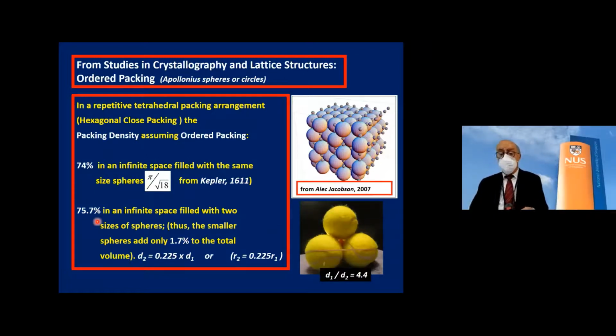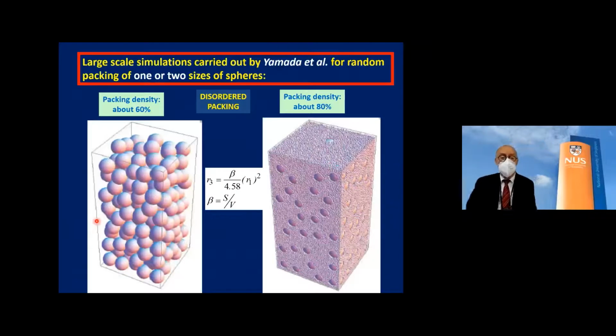But that tells you that if you want to increase the packing density, you better think hard about it. So now I go to this study, which was carried out by Yamada, I guess, can't remember, maybe 2005 or something like that. And in his study, he imagined that these big spheres here are red blood cells, and he wanted to add to them small particles of medication. And he ran a very large number of simulations, and he was able to then get the radius or the diameter of the particle that he needed to add to these spheres to get the highest possible packing density.